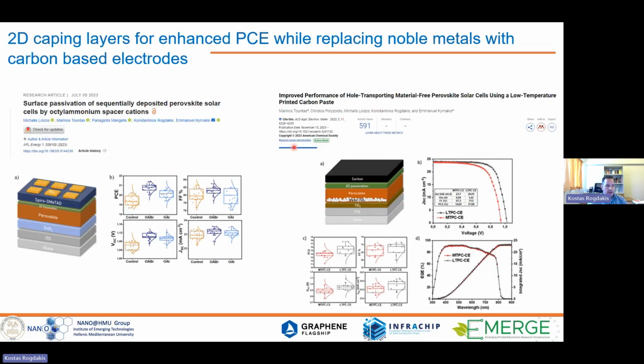Here, another direction was to find a way to improve the quality of the interface of the perovskite with some organic HTL, spiro layer. We have tested various 2D caps, 2D passivation layers, and we observed improved performance using this OABr material as a capping layer of our perovskite devices.